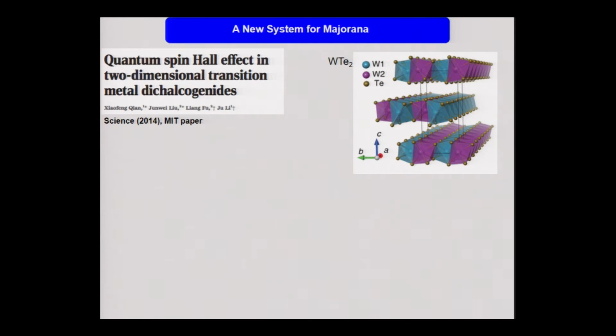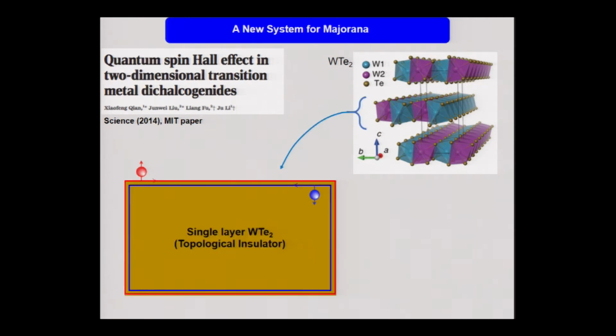They identify a new material, two-dimensional transition metal dichalcogenides, for example tungsten ditelluride, which is a layered material. Here I show the crystal structure. In each layer, you have three layers of atoms, and in the middle are tungsten atoms. Top and bottom, there are tellurium atoms. So they predict that if you can get a single layer of this material, then the single layer crystals behave just like the topological insulator that we mentioned before. So it's an essential component for the idea.